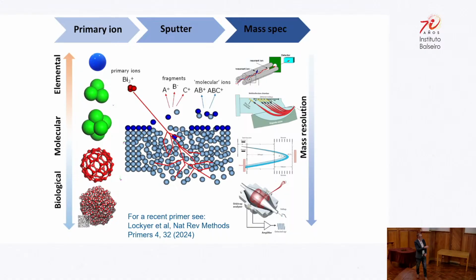Then we can increase the size of these clusters, and we do that because we want to cause less damage at the surface, until we get to these very large argon gas clusters or water clusters, which are very much gentler and cause minimal degradation to the material.